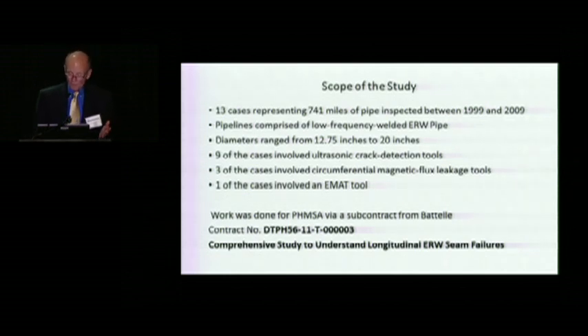You can't use it, can't let it go. But we did manage to get 13 cases, 741 miles. The range of age of these studies is a little old, but then we started this study in 2011, so we didn't have all the latest and greatest stuff. And you can see the range of pipeline diameters, and then we looked at 9 cases of ultrasonic crack detection tools, 3 cases involving circumferential magnetic flux leakage, and 1 EMAT tool, but as you'll see, it really wasn't a fair test of the EMAT tool. I'll get to that in a minute. This study was done, and it gives you the contract number and the title of the study here. And the phase 1 of this study is complete.